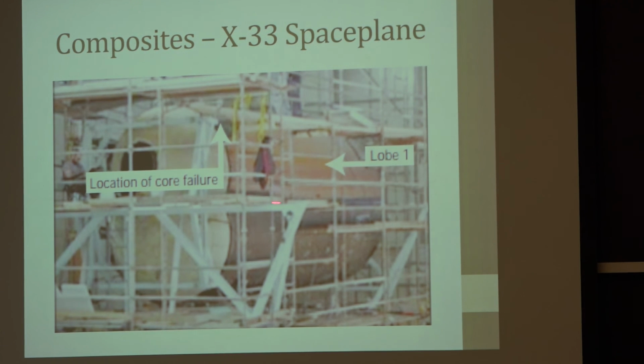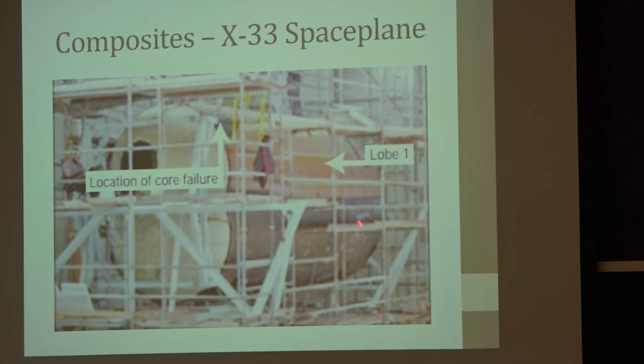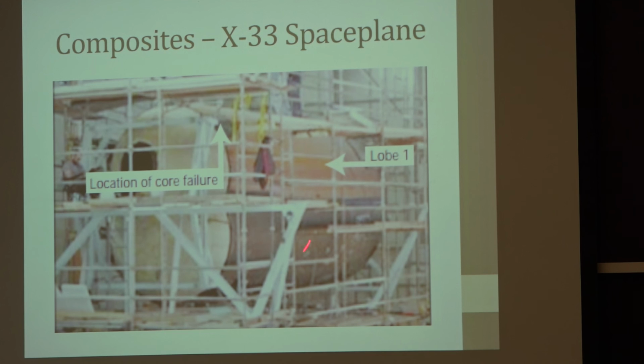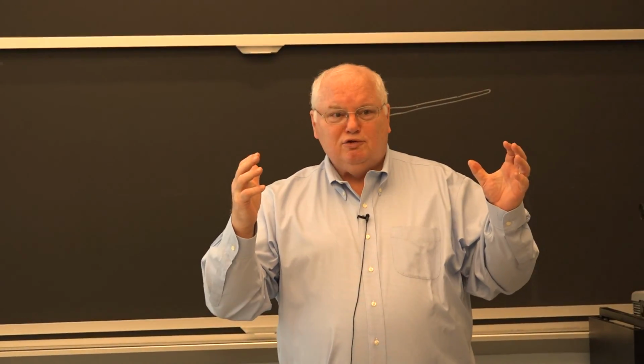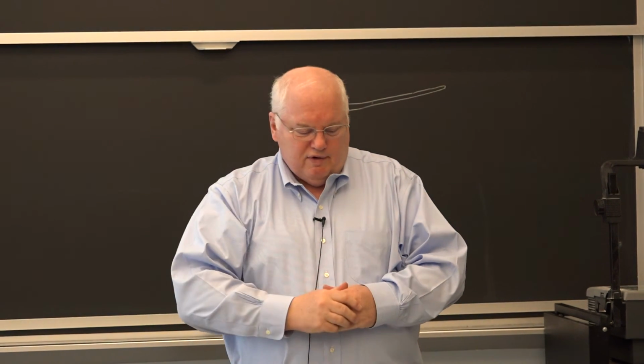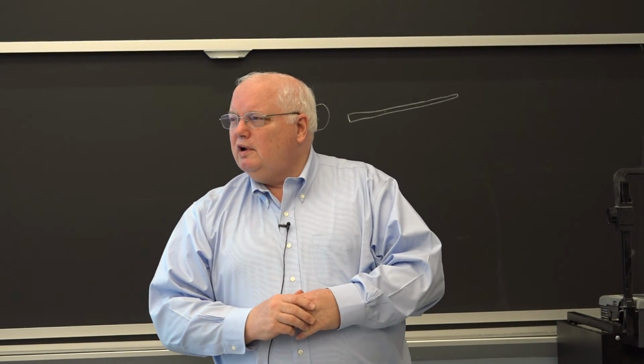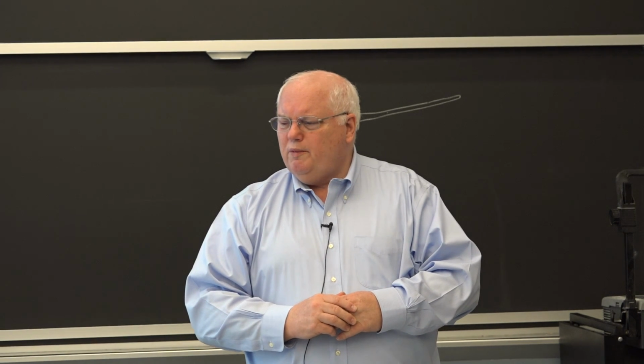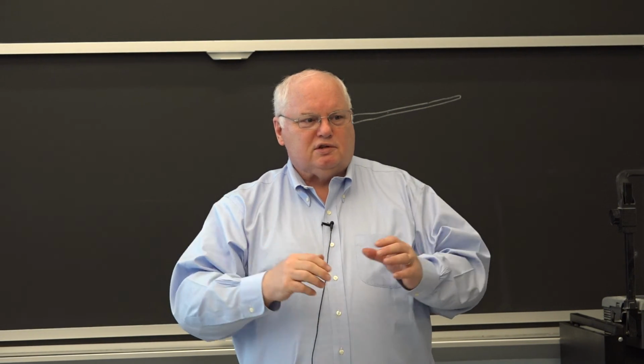So they take it down to Huntsville, Alabama, because not everybody has a test facility with enough liquid hydrogen to fill up something this size. This is scaffold in here, so this is about 20 feet tall. And you can see here's a lobe, here's a lobe. And they put it in test with the liquid hydrogen. Everything's just video. You don't have people around liquid hydrogen because if it goes boom, it's not a good day. And everything passes as they cool it down. They're warming it up. They're giving themselves high fives. And someone sees on the video, about 2 to 5 minutes after it started warming up, this pop, and a bunch of the frost comes off.